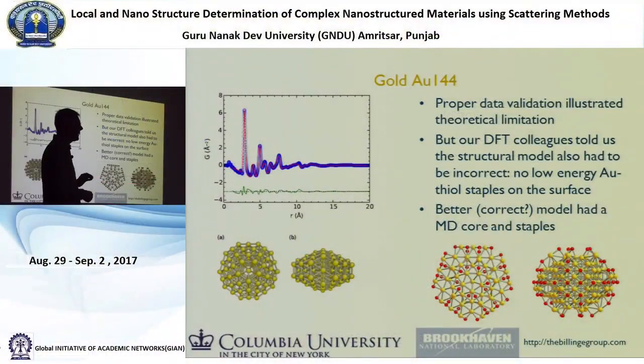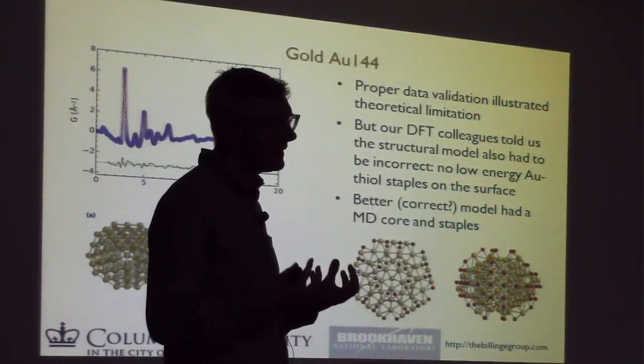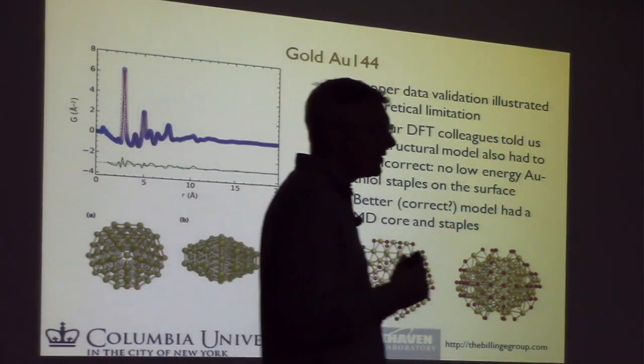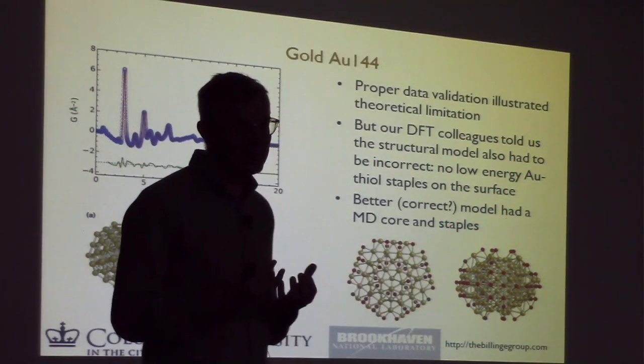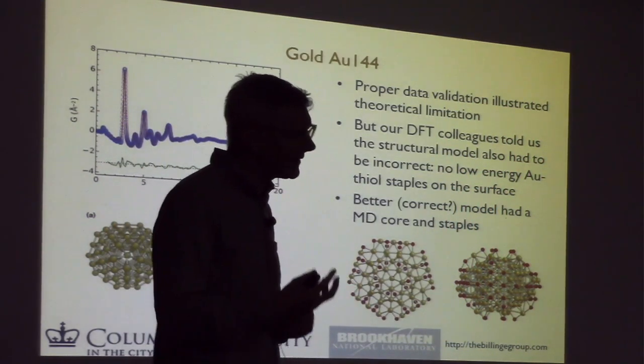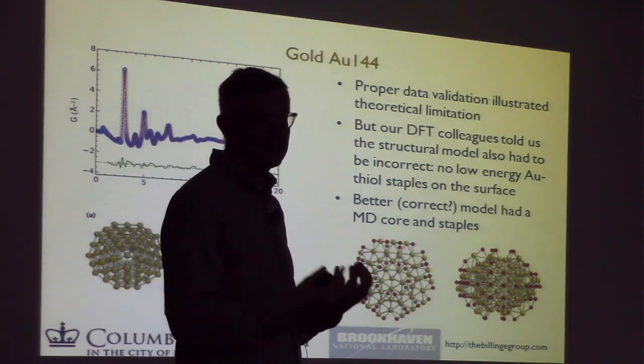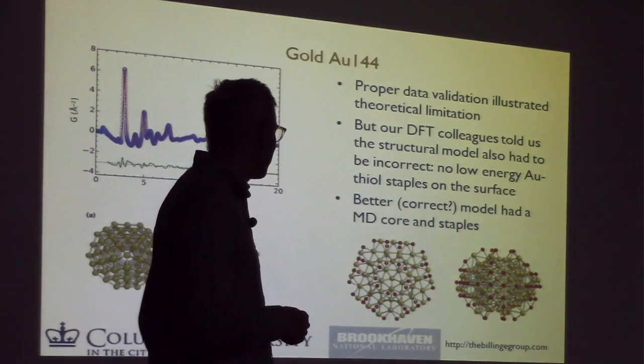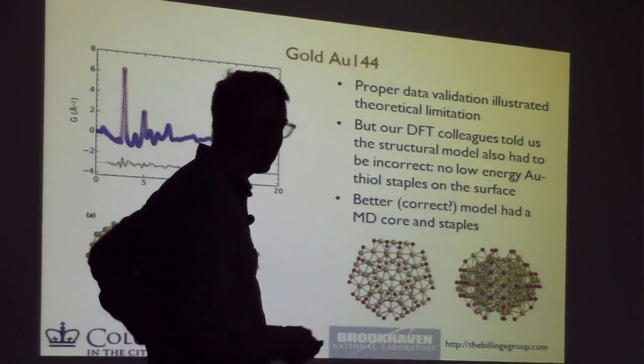But this was actually published in Nature Materials, and the interesting thing that came out of this study was that we went back to repeat the experiment. And when we repeated the experiment, we got gold clusters that had the icosahedral core. So it turns out that this gold 144 can form either with a decahedral or an icosahedral core. In fact, it's polymorphic. So it's the first gold cluster that's been discovered that's actually polymorphic. And we had some samples that were a mixture of both. It's actually very interesting. Such a small material, it's actually polymorphic, more than one structure.